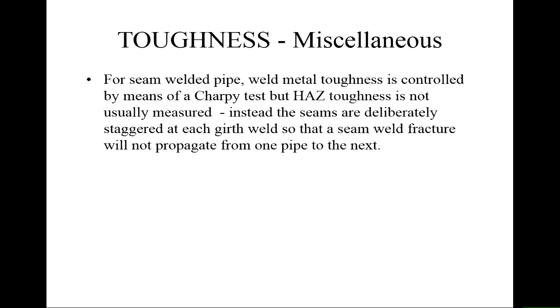But just to make sure that that's not going to be a problem, when you've got a segment of pipe that's being welded in the field, it might have a longitudinal weld along the pipe to make it, you make sure that that weld is staggered. It doesn't match up to the weld on the next piece of pipe and the next piece of pipe. So if a crack starts in the weld or starts in the heat affected zone, it will run along through that one section of pipe until it gets to the next pipe, which is at a different orientation, and then it will try to crack the pipe base metal itself. So you hope, you expect that you have got a failure which will only occur in one or two pipe segments and will not run on and on and on.